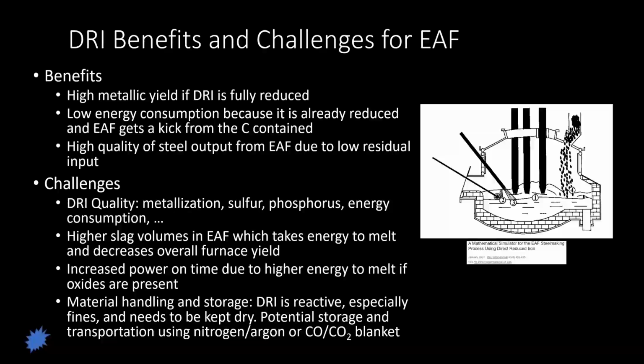Maybe not quite the same carbon content or energy benefit along with the electric arc furnace. Some other benefits are if it has high metallization, low energy consumption, and basically better quality of steel with low residual content. DRI quality matters - metallization is a big deal, especially if it's coal-based, along with sulfur and phosphorus, and then energy consumption. These are all concerns when talking about DRIs.